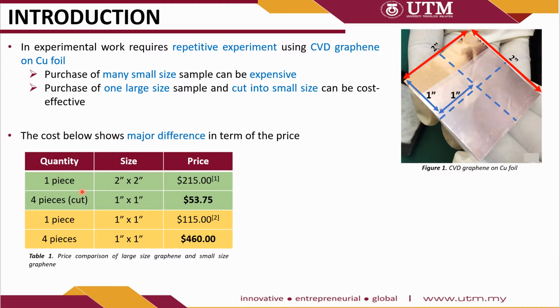One piece of 2 x 2 inch graphene costs around $215 and it can be cut into 4 small pieces with size 1 x 1 inch. When the cost was divided, one piece of cut CVD graphene on copper foil only costs $53.75. This is way cheaper compared to buying 4 pieces of 1 x 1 inch CVD graphene on copper foil separately.